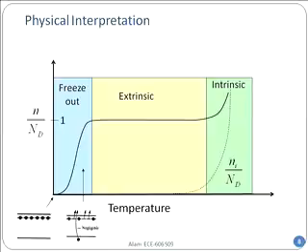Now a little bit later, when you increase the temperature a bit more, the donors will easily give out electrons to the conduction band because it needs only 100 millielectron volts. There will also be a few from the valence band, but only a few, because it's such a big jump, 1 eV or so. Therefore, in that region, the electron concentration will be approximately equal to the number of donors you have.